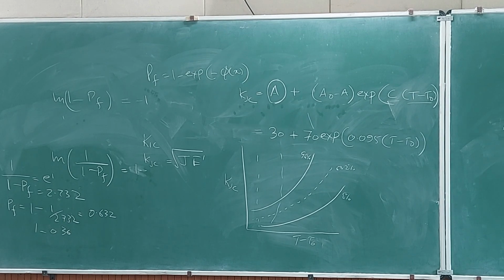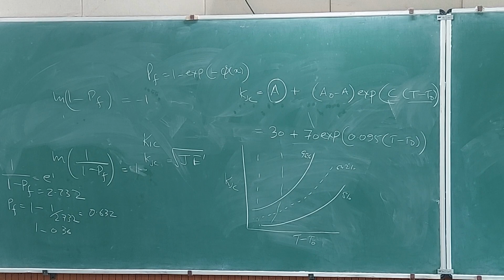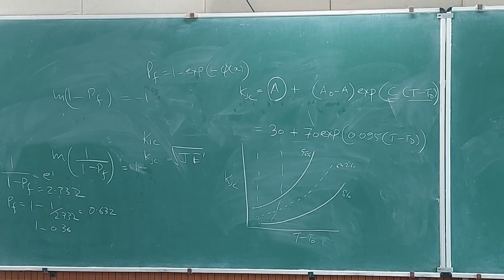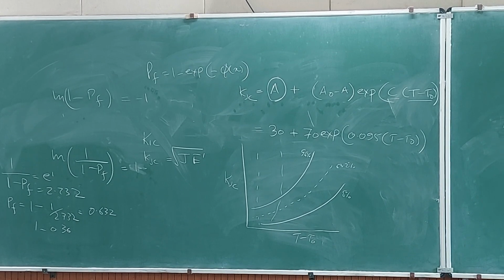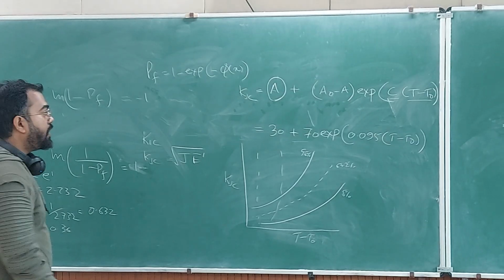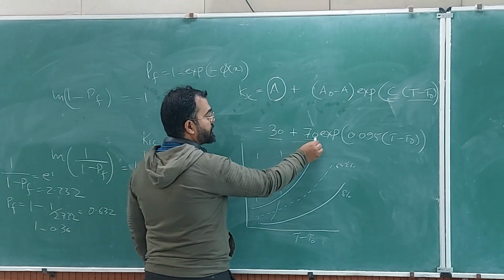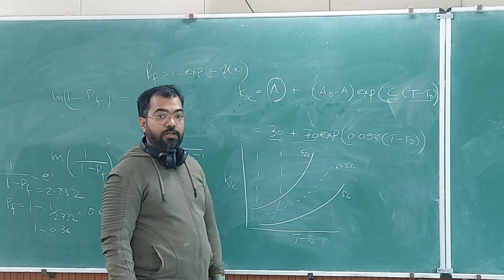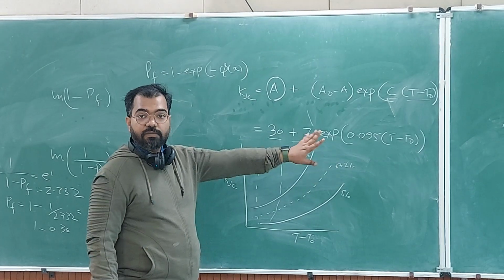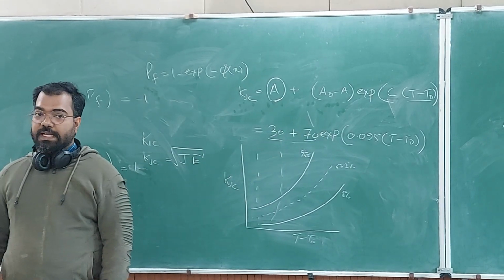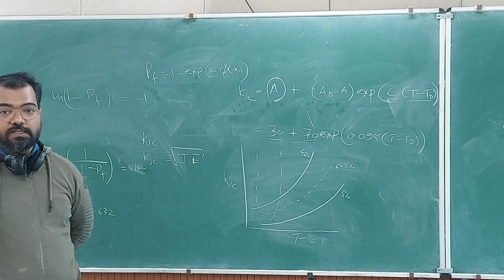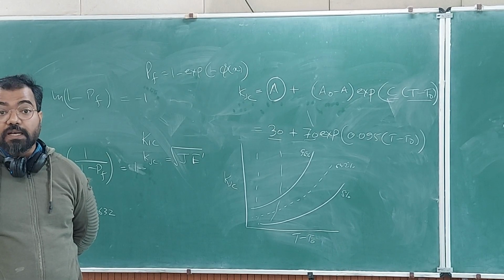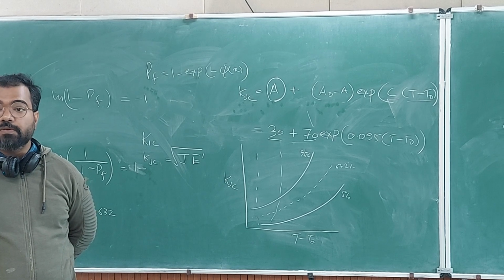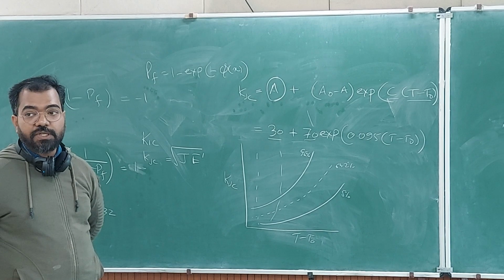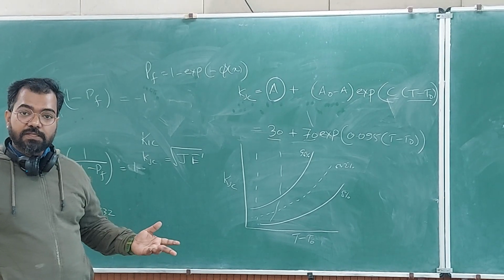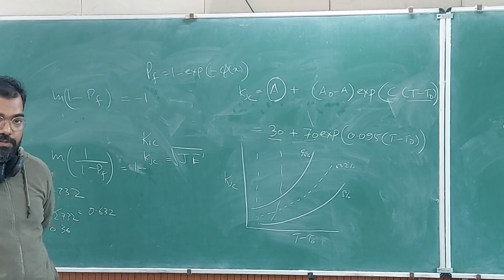So it can work for any ferritic steel. It will probably not work for non-ferritic BCC alloys. In theory, for non-ferritic BCC alloys, these values will change. Also, you might have to look for a KJC which is not 100. If you find a BCC alloy which has very high toughness in comparison to ferritic steels, then 100 MPa root meter becomes very low for them. For example, for HCP, you will not find a single test which can give you 100 MPa root meter. So there this curve is not valid, and you have to redefine these values.